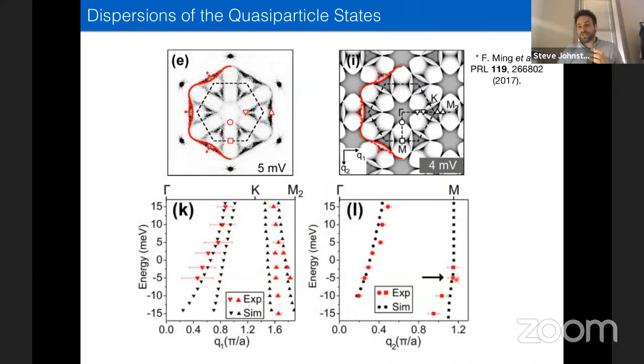To convince you of this, we can actually do this very systematically. So what we do is we take the experimental quasi-particle images, and we drop markers down on various features. So squares and triangles correspond to different features that we'll track. We put markers down on what we think are the corresponding features in the experiment. So for these triangles, there's sort of two things we could identify, so we put them both down here. And then we track it as a function of bias voltage in the experiment, and we do the same thing with the theoretical band structure, and we compare the two. So that's what's plotted here.